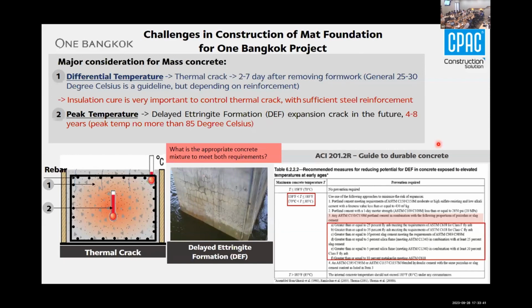Before doing that, when we start the meeting with all parties before the project begins, for mass concrete and a mat foundation like this, we have to be concerned about two items. The first one is the differential temperature of the structure. In general, the core of the concrete gives a high temperature, and the edge of the structure gives a lower temperature. So if there is differential temperature, the concrete can shrink and expand differently, which means there is potential to crack. That is a thermal crack. We have to be concerned about this because we have to put some rebar to control the crack around this area.